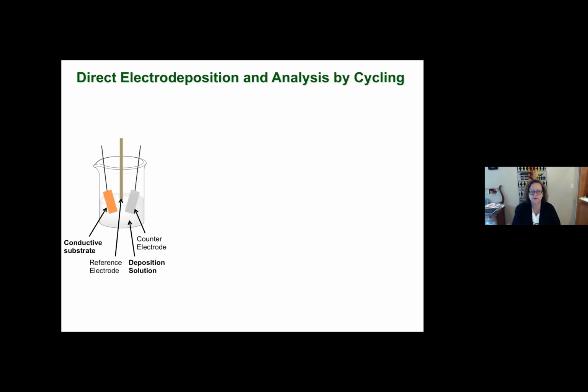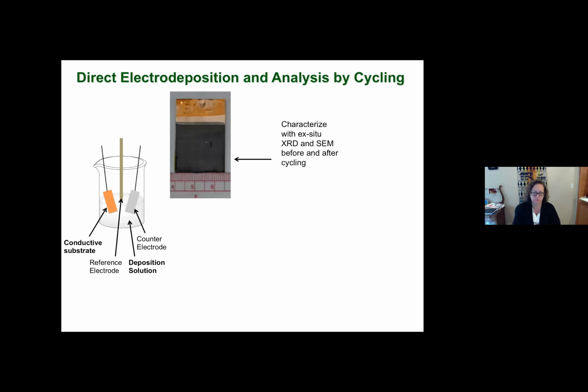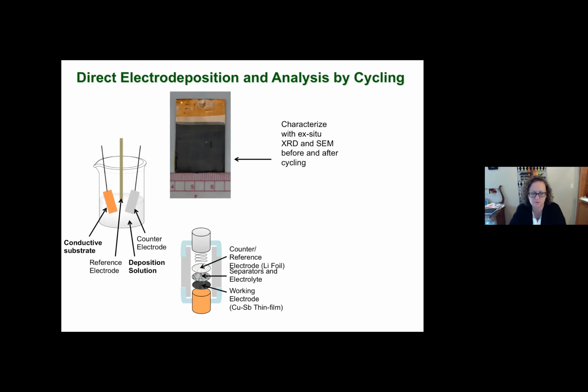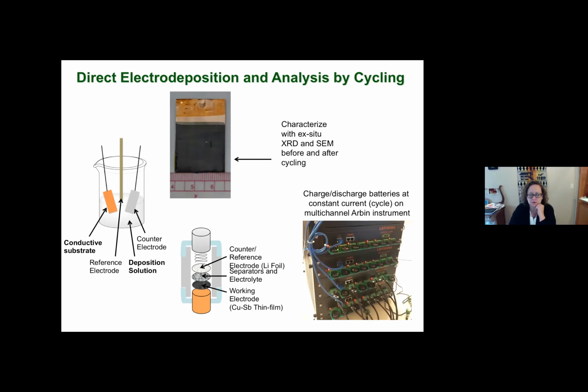Okay, so in my academic group, we just do normal electrodepositions in beakers. You know, we think a lot about things like the counter electrode placement, surface area, pre-treatment of the substrates, and how to clean the surfaces. We make pretty reasonably sized foils that we can characterize with X-ray diffraction, scanning electron microscopy, and then we can punch out discs from those foils and assemble them in Swagelok cells. We use these because we can disassemble them pretty easily at the end and do postmortem analysis of what the films look like. And then, once we build these cells, we can put them on a cycler and do all the electrochemical experiments that are normal for batteries.